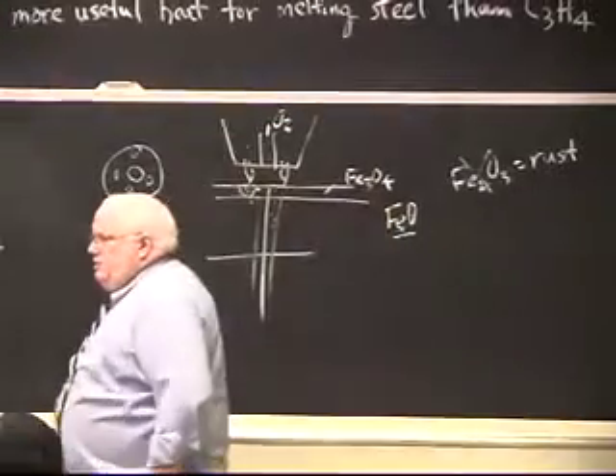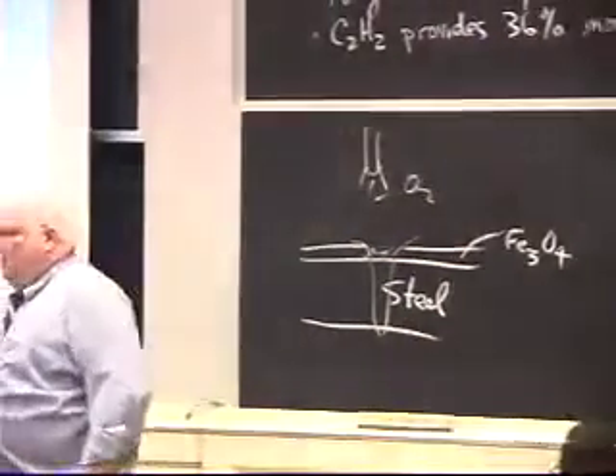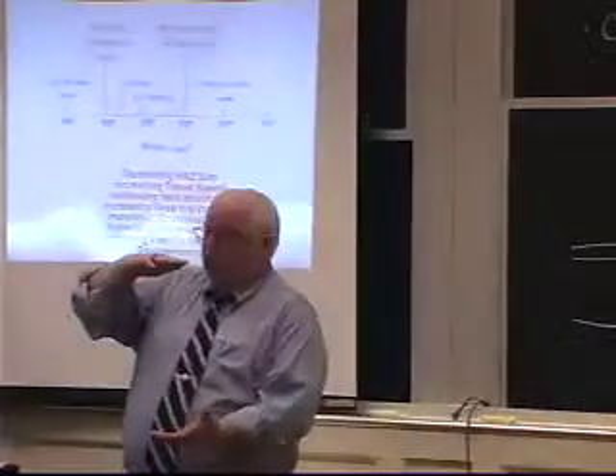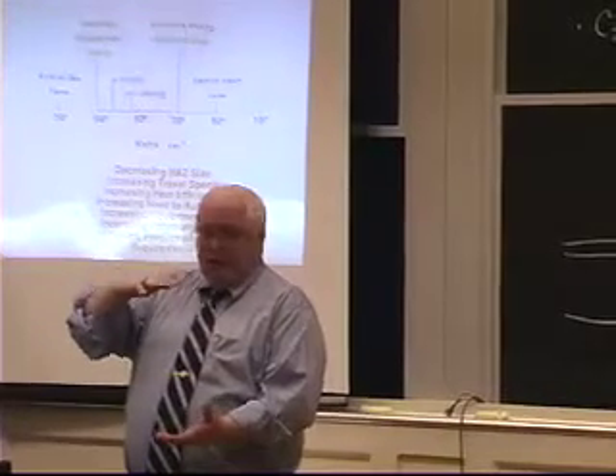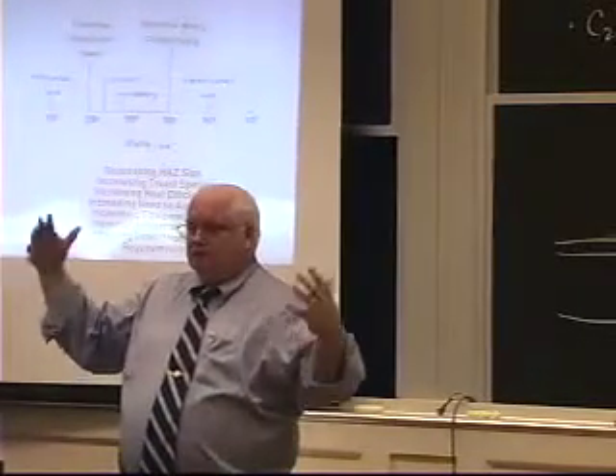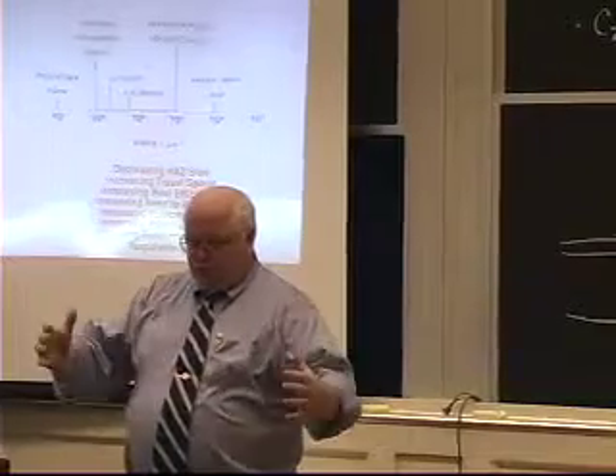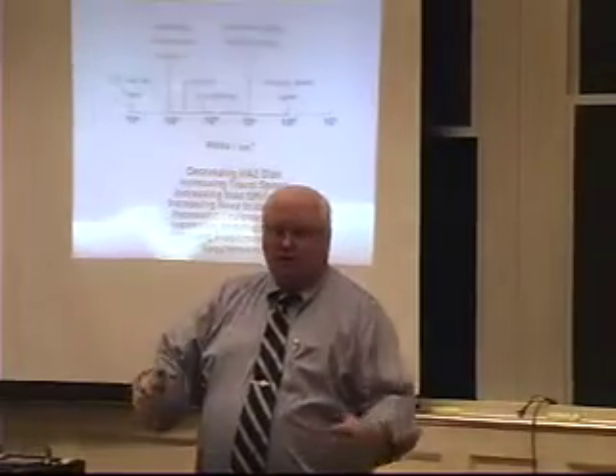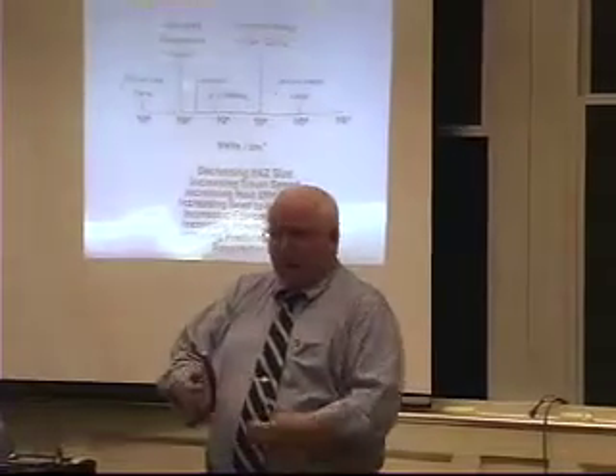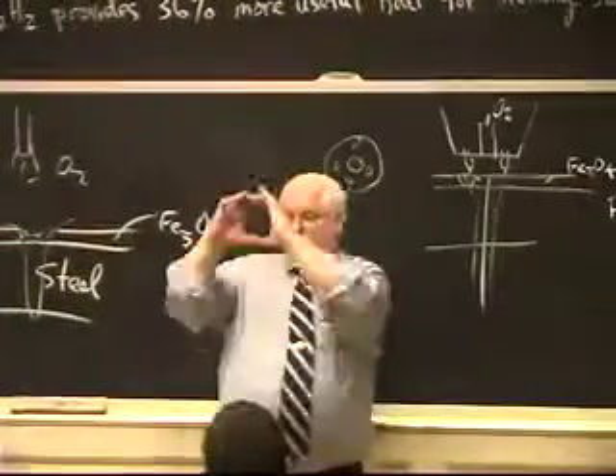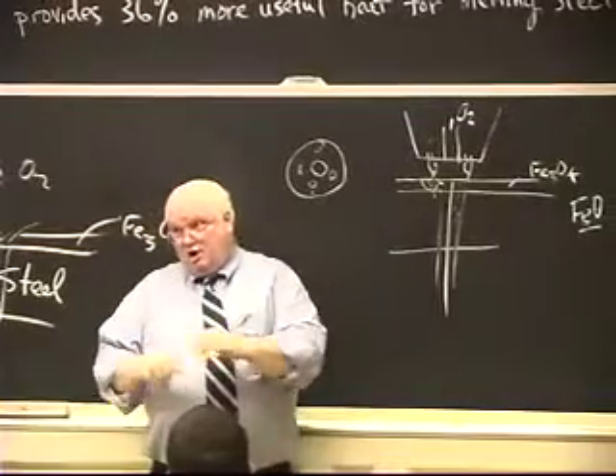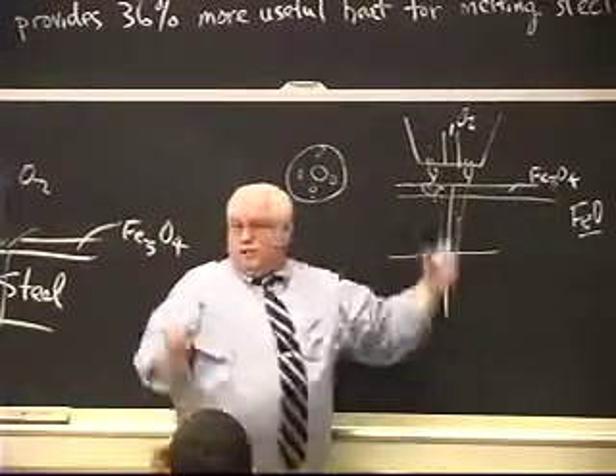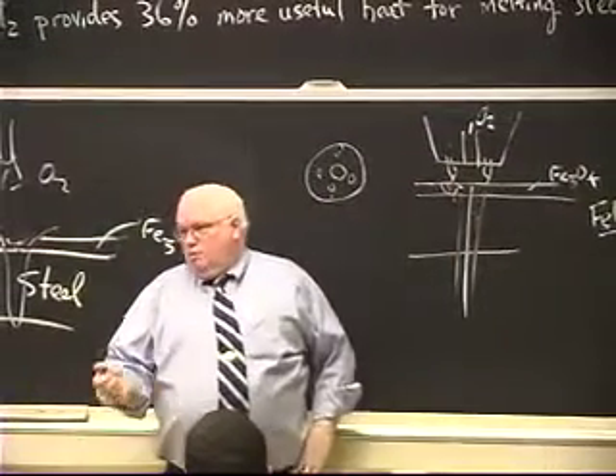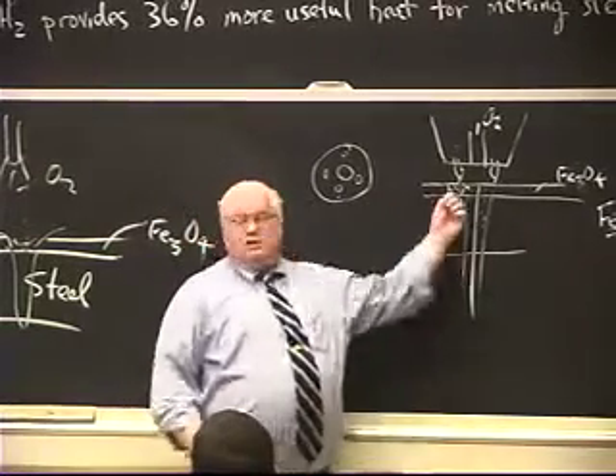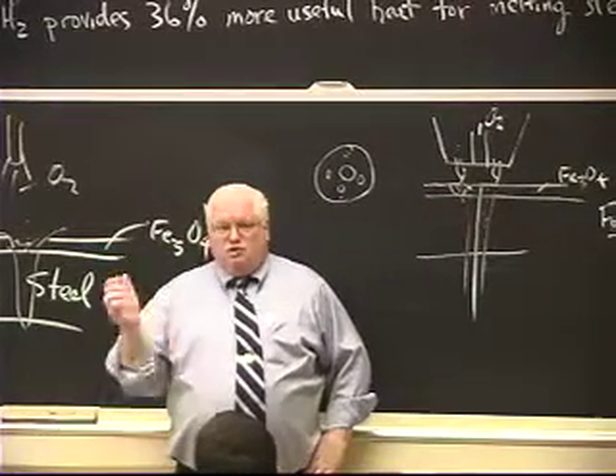The thickest I've ever seen cut, personally, is about 12 inches. That 14-inch piece of weld that I brought to you, the guy had this truck of compressed oxygen, and he had 2 propylene tanks about this big, and he had a lance that would light off the propylene just like this. Now the whole lance was about that big around. He wasn't making a small cut, he was going to be making a big cut. And the hole was probably a half-inch hole of oxygen, and he would warm it up, take about 30 seconds to heat this surface, and then you turn on the oxygen and you should have seen the sparks.